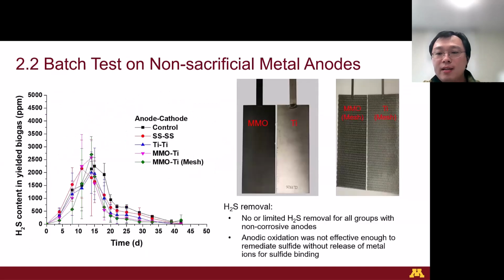So next, we tested the non-sacrificial metal anodes, aiming at reducing the anode material consumption. They include stainless steel, SS, titanium, Ti, and mixed metal oxide.